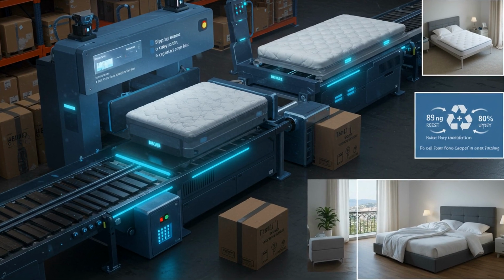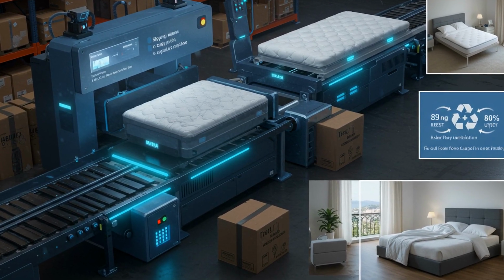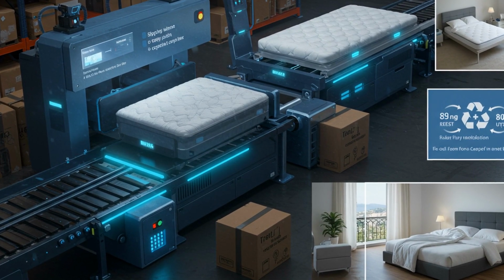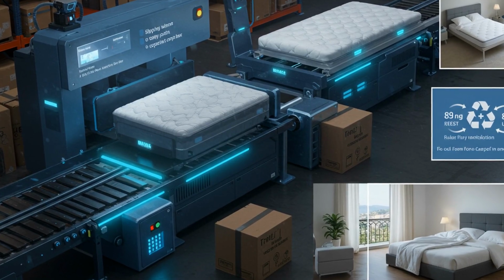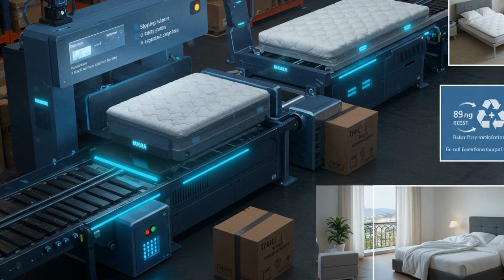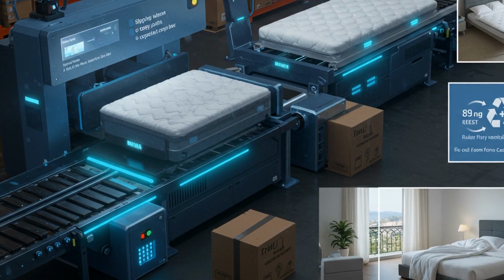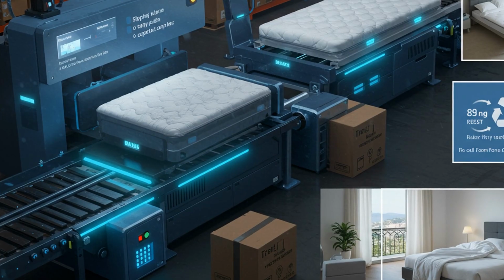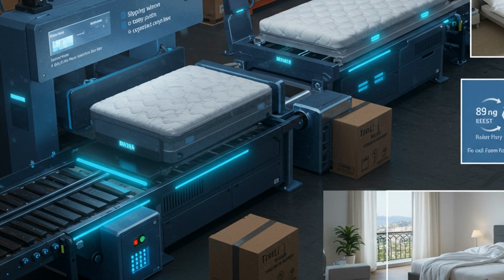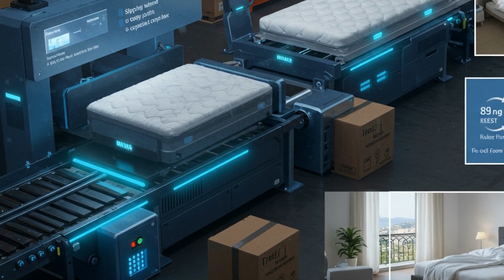The final act is packaging and delivery, but the engineering story continues. Mattresses are vacuum compressed and rolled into boxes, which reduces transport volume by up to 80%. Packaging design must balance protection with breathable materials to allow residual gases to escape. At the retail or home stage, the foam decompresses over hours to days, completing slow recovery. Sustainability is now central. Manufacturers explore bio-based polyols derived from soy or recycled carbon streams, and physical blowing agents like water or CO2 replace older chlorofluorocarbons. End-of-life plans include recycling into carpet padding, underlayment, or energy recovery.